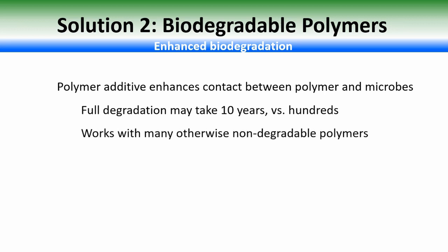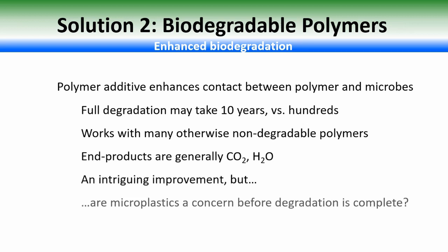This technology has the advantage that it seems to work with a wide variety of polymers, converting them from non-degradable polymers into those that, if not degradable, are at least much less non-degradable. And the polymers for which this option is effective are those that already provide reliable properties and which are available at low cost. So, while the environmental benefit may not be as great when compared with biodegradable or compostable materials, in some ways, this may be a more commercially viable step in the right direction. The end products of this degradation process are generally carbon dioxide and water. So this option is intriguing in a lot of ways, but I still have a question about whether this technology also generates microplastics along the way to a total conversion that may not be complete for several years.